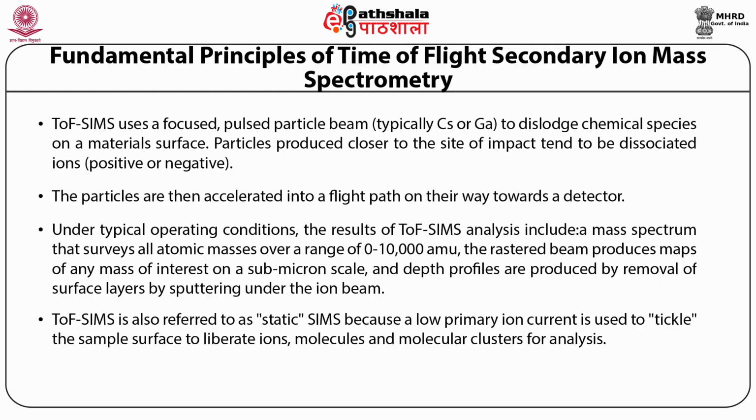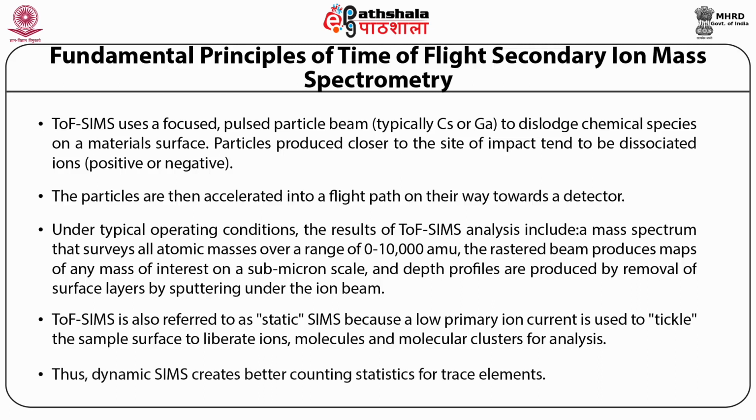In contrast, dynamic SIMS is the method of choice for quantitative analysis because a high primary ion current results in a faster sputtering rate and produces a much higher ion yield. Thus, dynamic SIMS creates better counting statistics for trace elements.